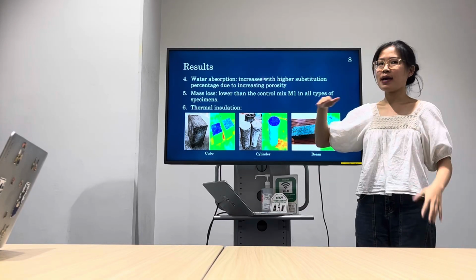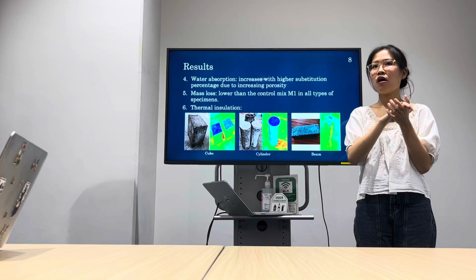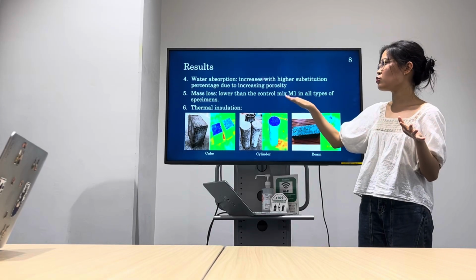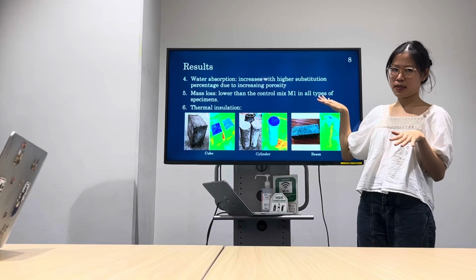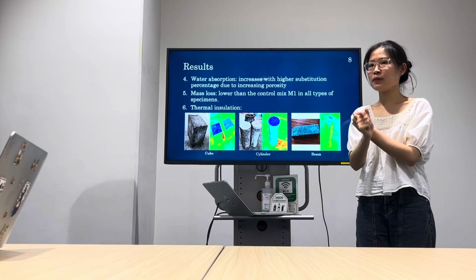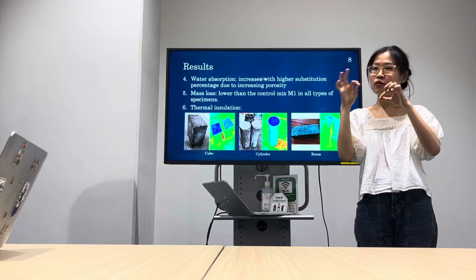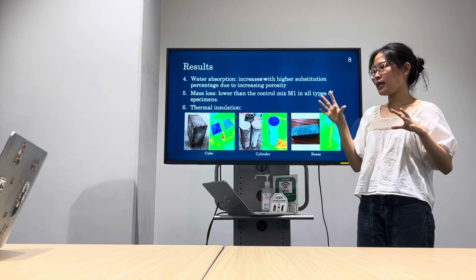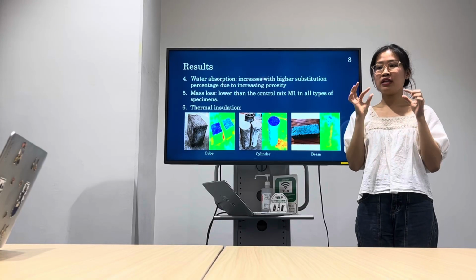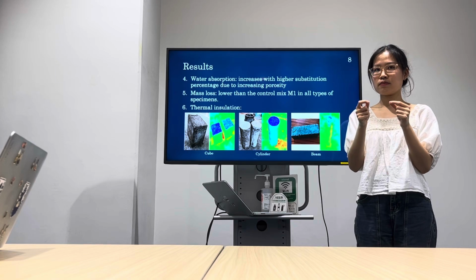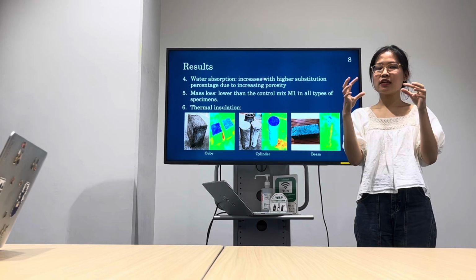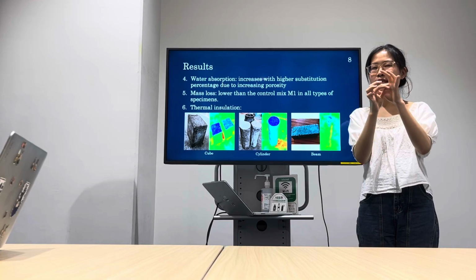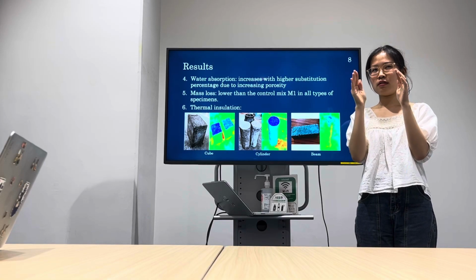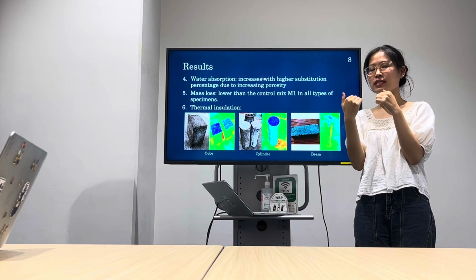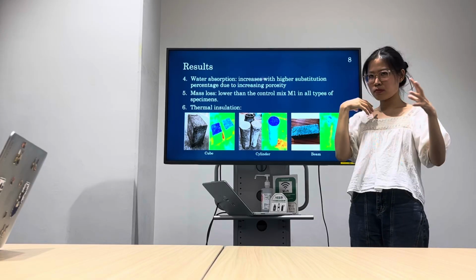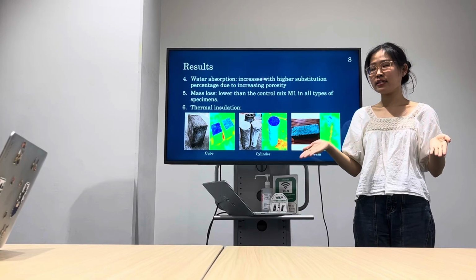And then mass loss. The mass losses of M2 to M5 are all lower than the control mix M1 in all types of specimens. This is because LSP can fill the micro voids of concrete, and coconut fiber is very crack resistant. Moreover, because it is crack resistant, less water can get inside the concrete, and that's why degradation will be less likely to occur.